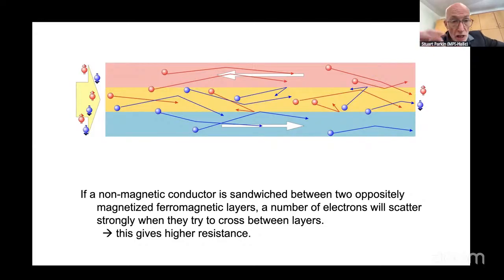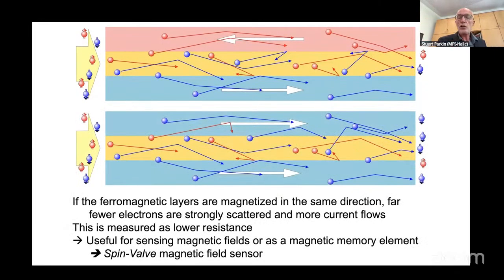So now when you introduce current from the left-hand side, the current in the blue layer will be carried by the blue electrons, and in the red layer by the red electrons. But because this copper layer is so thin, the electrons are not just traveling in the direction of the current, they're traveling in all directions. So the red electrons will cross the copper layer and be scattered in the blue layer and vice versa. So in this type of structure, all the electrons will be scattered somewhere. And therefore, the resistance will be higher than in the same structure where the two magnetic layers have their moments parallel. In this case, it's like a short circuit. The blue electrons can travel without a lot of scattering, and so the resistivity is reduced.